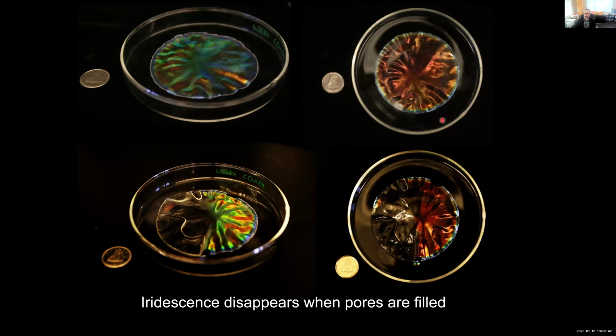Here you can see a photograph of the red film from the top, and if you tilt your viewing angle, it turns blue or green because there's a sine theta angle dependence on the color. If you add water to the left side of the film, it again goes inside the pores and makes it colorless and transparent in that region, and it's completely reversible. We can use these for humidity sensors, for instance.